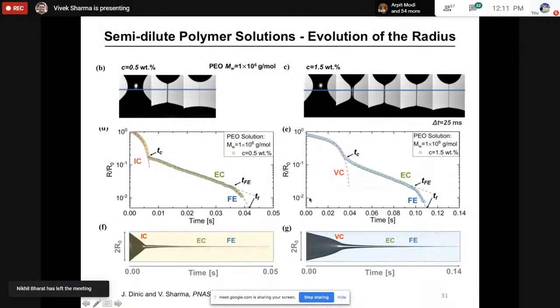So here is an example of a data set that we get using dripping onto substrate. And what we highlight here is that as we vary the polymer concentration, the actual solution viscosity is low enough that you can see the inertia capillary to elastic capillary to finite extensibility transition. But when we go to higher polymer concentrations, the polymer solution viscosity becomes high enough that the initial regime is visco-capillary, followed by elastic capillary, and then finite extensibility.